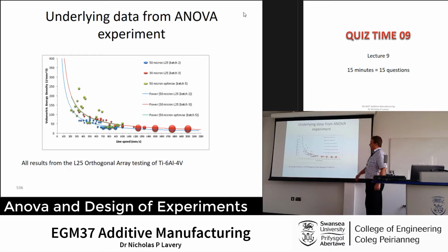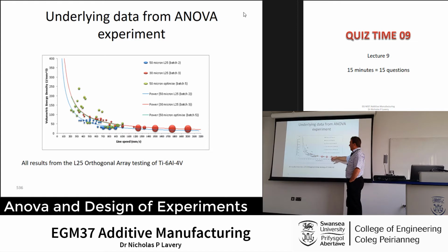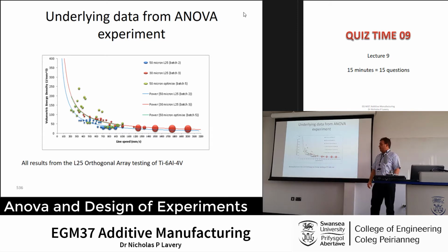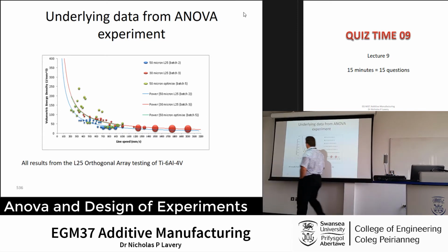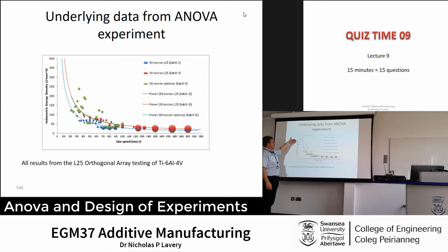This is another result over many different tests. You can see this is for titanium 6-4, and this was using an L25 orthogonal array. So populating it, you can see different layer thicknesses. You can see the bubbles are scaled according to the level of porosity in the part. So you've got the energy density of the laser, and then you've got the speed of the part.